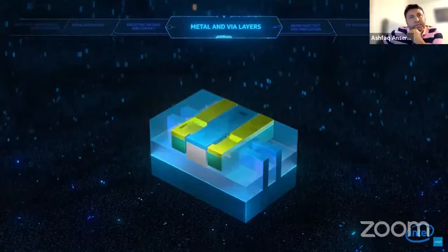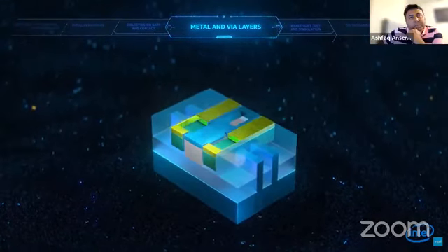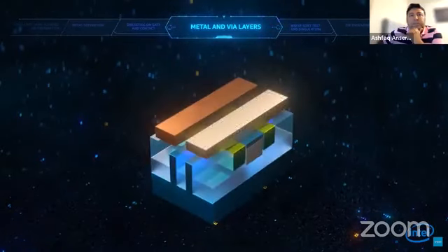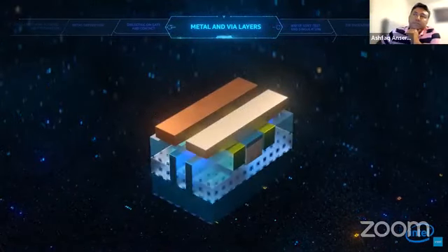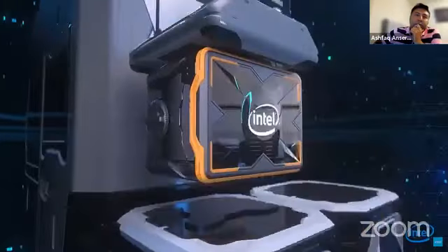Now, the dielectrics are etched selectively to expose only the desired part to connect to the first metal lines. This is done through an innovative via etch and deposition scheme, allowing contact over active gate to happen. Finally, dozens of layers of metal interconnect lines are added to complete the circuit.